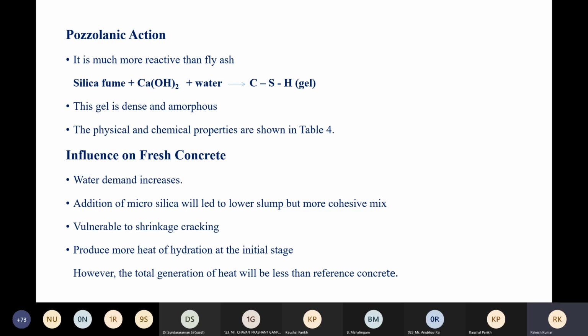What is the influence when you use silica fume in the concrete? What is the influence on the fresh properties? With silica fume, water demand increases. In fly ash, as I told you in one study, if you replace 30%, water demand decreases by 7%. But when you use silica fume, water demand increases because it is very fine. Addition of microsilica will lead to lower slump, but a more cohesive mixture.